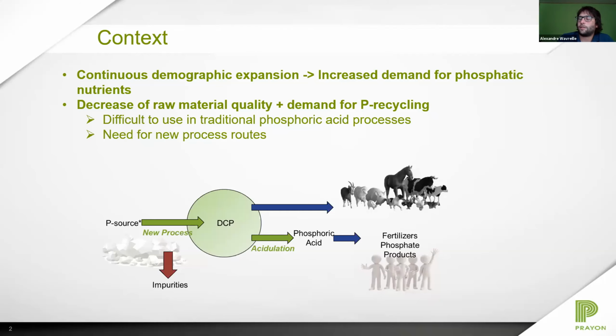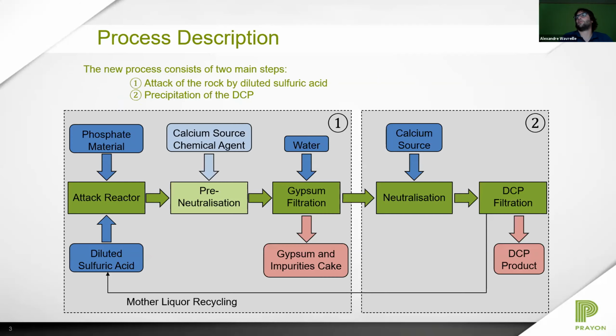In this case, we developed a new route that permits us to upgrade low quality phosphate sources into DCP, which can be used directly as feed grade dicalcium phosphate, or also it can be used as an intermediate to produce phosphoric acid of better quality. So a little process description. It is a two-step process.